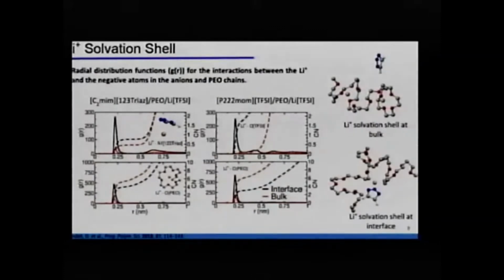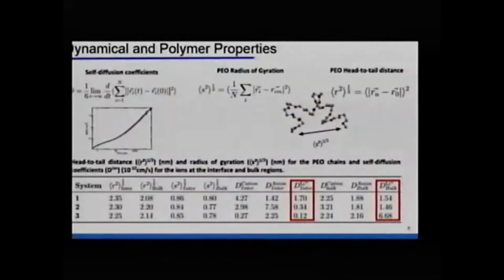And if we look here at the phosphonium system, we see a huge decrease in relation to the triazolide system. This is because in the density distribution, we saw a smaller peak in the interface than in the imidazolium system. Also, if we look at the coordination numbers that are close to 6, we can see some indications of the formation of a structure that we call the crown structure. I said in the beginning that the PEO can adopt a helix structure, like DNA, and inside this helix structure, the lithium can go back and forth, so this increases the transport of lithium in this system.